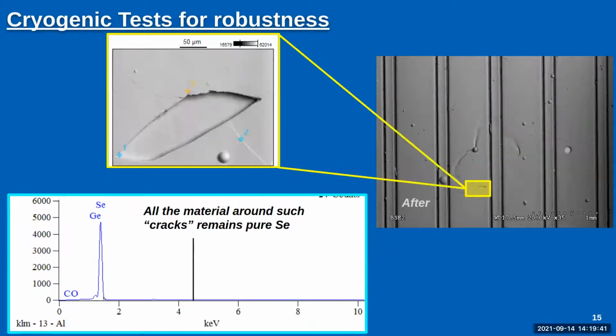And if you look at some of the other areas, you can see that in the surrounding cracks, it remains pure selenium. So all in all, after a single cryocycle, this board actually looked like it was in relatively good and robust shape. And there are various methods that we could use to try to improve the evaporation methods that would also then improve the performance during cryocycling.